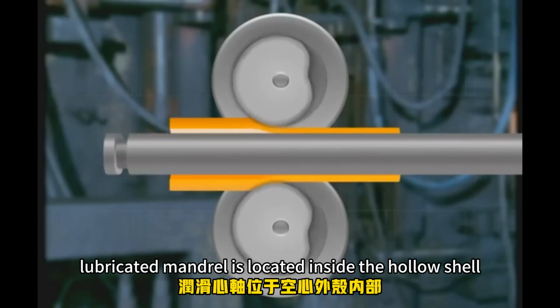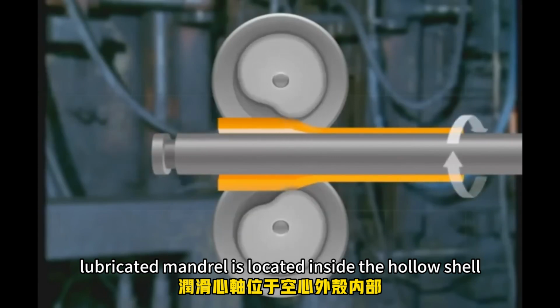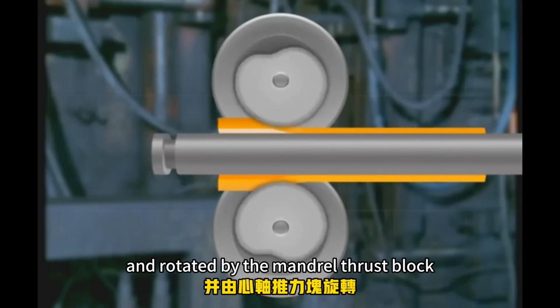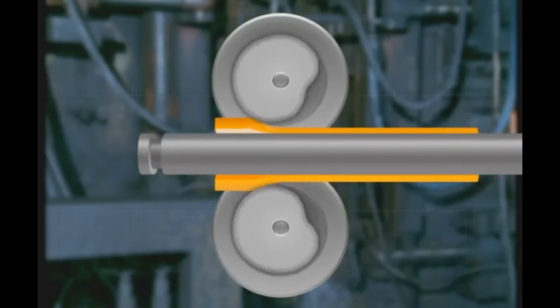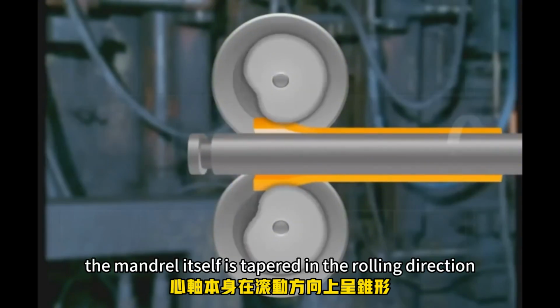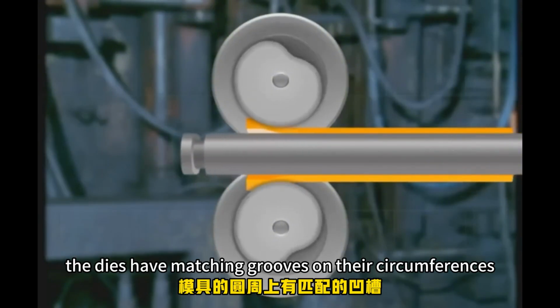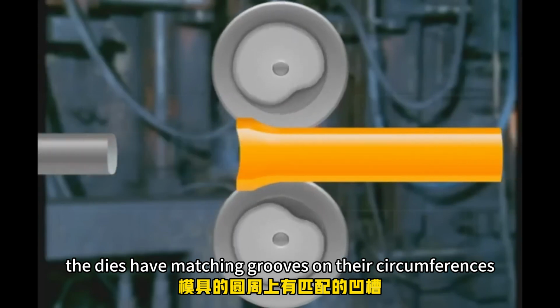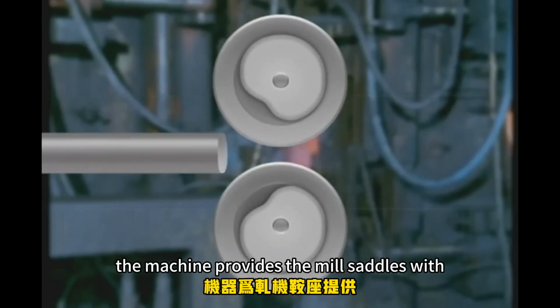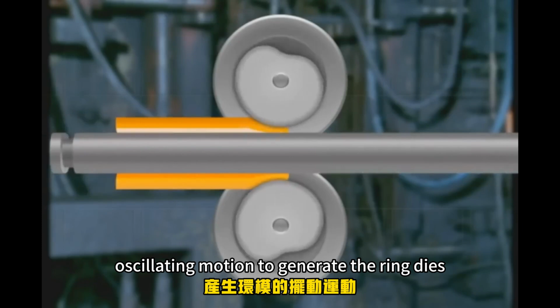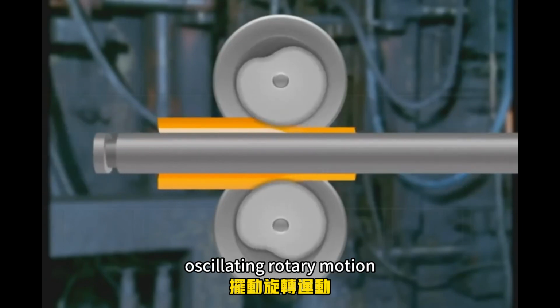The lubricated mandrel is located inside the hollow shell in a fixed position and rotated by the mandrel thrust block. The mandrel itself is tapered in the rolling direction. The dies have matching grooves on their circumferences. The machine provides the mill saddles with oscillating motion to generate the ring dies' oscillating rotary motion.